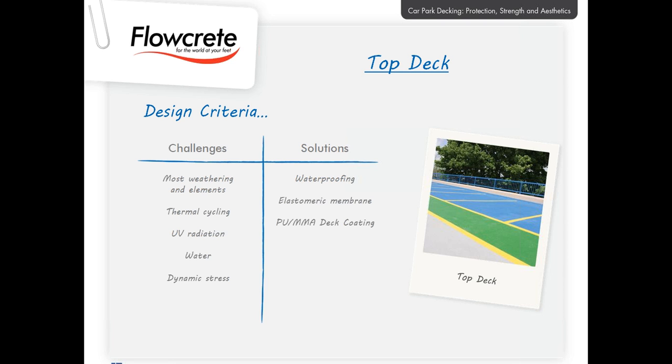However, in instances where there is no underlying DPM solution or where it has been damaged, a positive side, moisture-tolerant primer, or a breathable water-based floor finish will be required to prevent any damage to the final finish. The installation of a positive side DPM will not only allow moisture to pass through, but will also disperse any moisture vapor across a large area, and therefore prevent any point load pressure from damaging the final surface products over time.